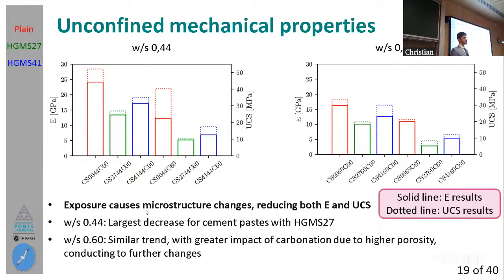What we can see in general terms is that in the first group, there is a decrease in all of these unconfined mechanical properties when we replace cement by hollow microfillers, from this to this, and then from this to this. So we have the lower value of these parameters for the cement paste in which we have replaced partially cement with a weaker sphere.